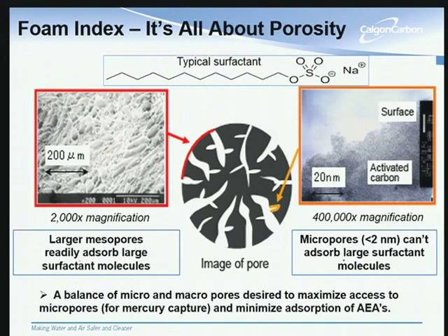Okay. Why is that? One of the big differences between bituminous coal and lignite coal is lignite has far more volatile matter in it. So when you go through the thermal steps and you blast it all out of there, you naturally create far more of a mesoporosity. So these are some of the larger pores. And those larger pores are good at absorbing larger molecules, which includes air entrainment additives, which are surfactants, basically. They're these long, greasy molecules you'll see here.